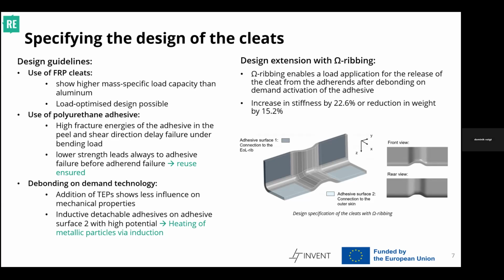And second, in numerical studies, I showed that it increases the stiffness significantly. My results showed either an increase in stiffness by 22.6% or a reduction in weight by 15.2%, depending on the design target.